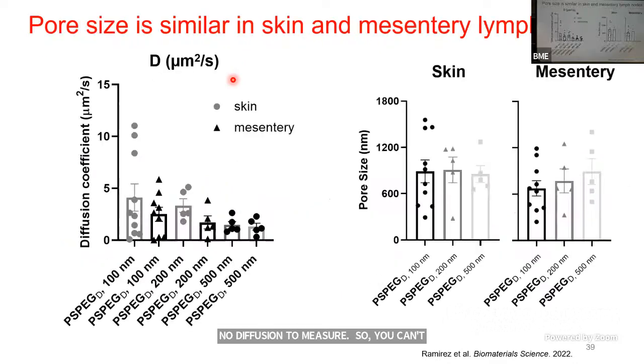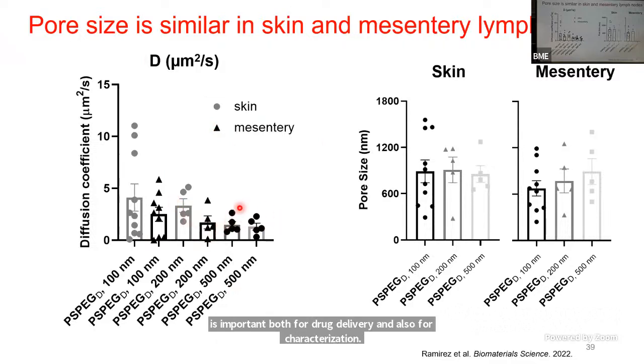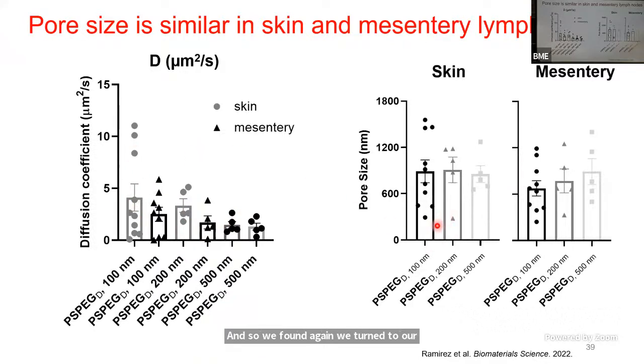And so when we extracted the pore size, and there's a reason why I'm showing you all of these dots, the pore size is directly related to the diffusion coefficient. So you can see that there are some decreases, but you can also see that there's a lot of variability both in the diffusion coefficient and also the pore size here. So we're starting to think about, oh, okay, there's a lot of differences here. Each individual point is a data point per mouse. And for each mouse, we collected at least two lymph nodes and more than 100 particles were tracked. So lots and lots of particle data here.